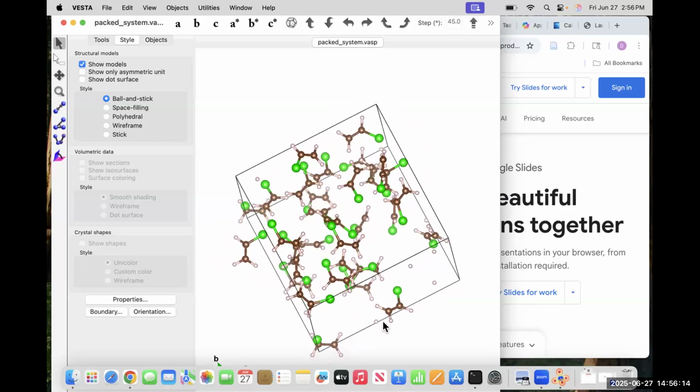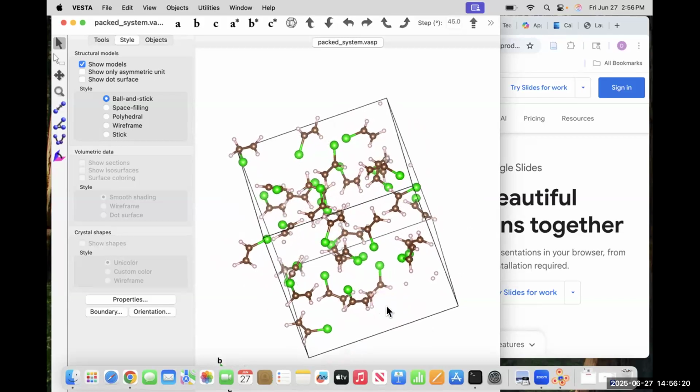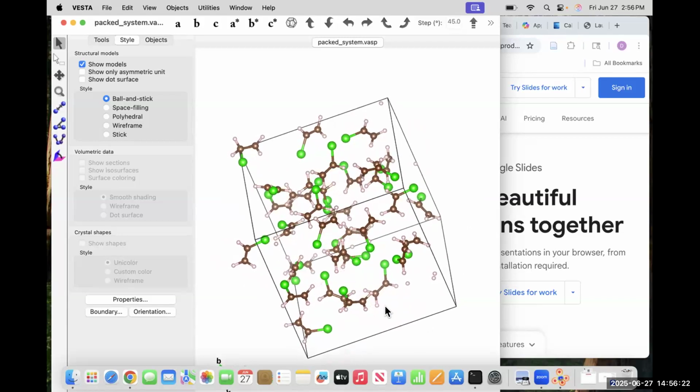Right, so if we don't see anything crazy, then that's probably a good sign. Generally speaking, I would always say, when you start a big calculation, take a few minutes to take a look at the system. If you see things that look like atom soup, where the atoms are crunched together, then something is probably wrong, and it's not worth the time to run the calculations on those.